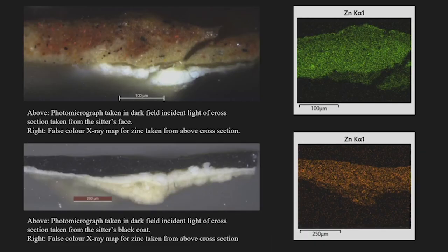What was interesting about the elemental investigation of these pigments was that whilst undertaking elemental mapping of small cross-sections taken across the painting, each paint layer, including the dark passages of paint, contains zinc. The fact that each layer contains this element provides evidence that the compound zinc stearate is an additive in this paint. This finding is indicative of commercially available tube paints of the period, such as those produced by Winsor and Newton, where zinc stearate was used as a dispersing agent.